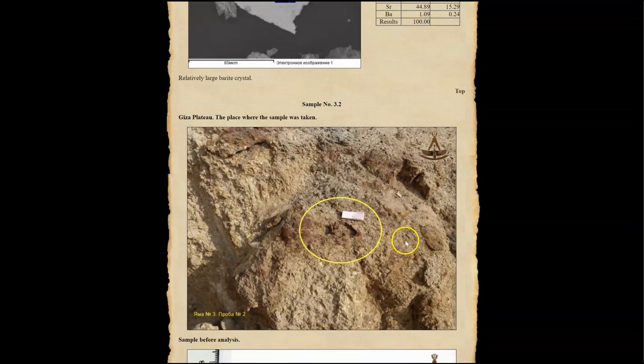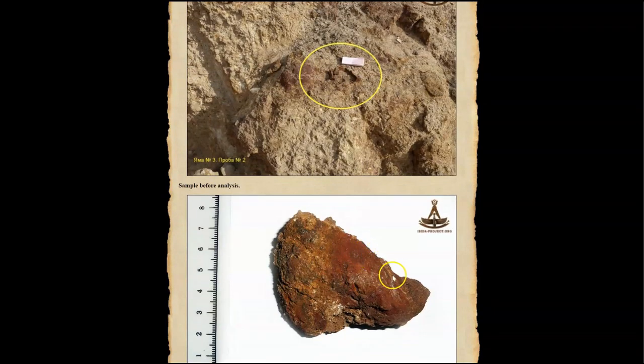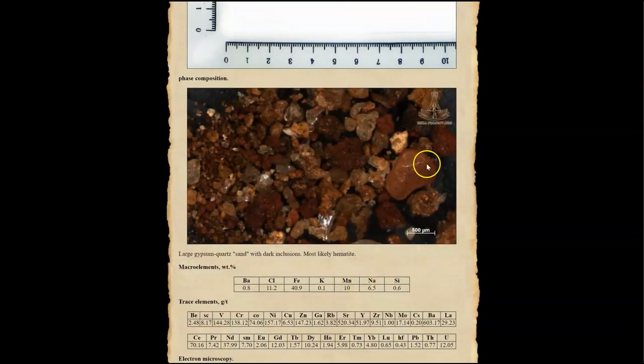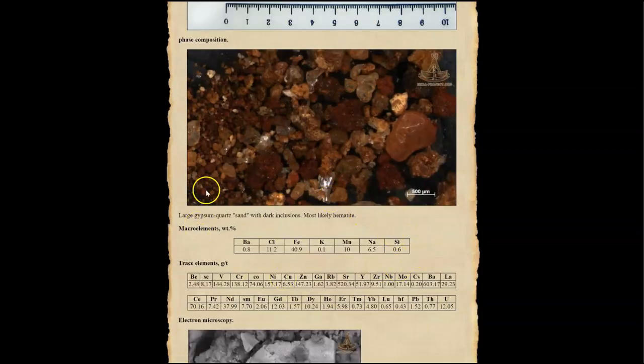And the next sample location here. An image of the material and a close-up. And the macro element analysis here, 40% iron, 11% chlorine, 10% manganese, 6% sodium, 0.8% barium, and 0.6% silicon. And these macro numbers, once again, do not have any carbon or oxygen listed. Trace elements here, which we will take a look at comparing the differences in these samples at the end.